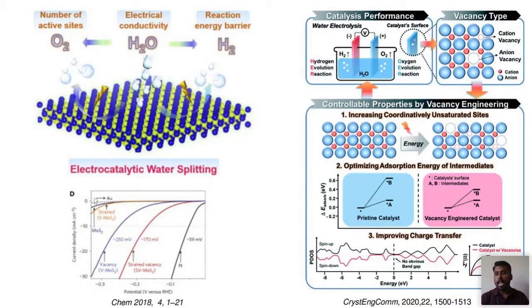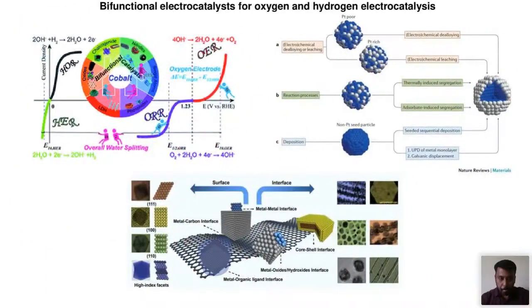You can knock out oxygen from the metal oxide surface, and you can create an oxygen vacancy. You can knock out a metal or an anion or a cation from the surface, and you can create cation and anion vacancies. So whenever you introduce a vacancy or defect, it can also increase the activity. Increasing the coordinatively unsaturated sites can also lower your surface energy, and it can also increase the activity. So optimizing the adsorption energy of the intermediate is very, very important. If you have a minimum adsorption energy, then the activity will be much higher.